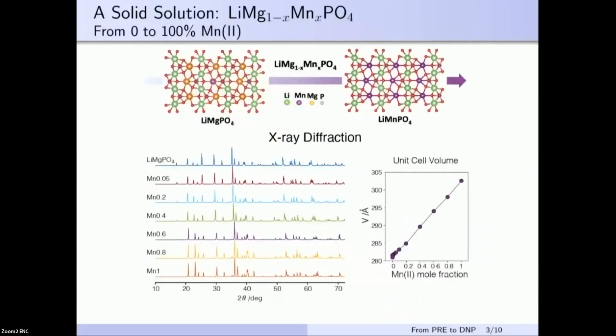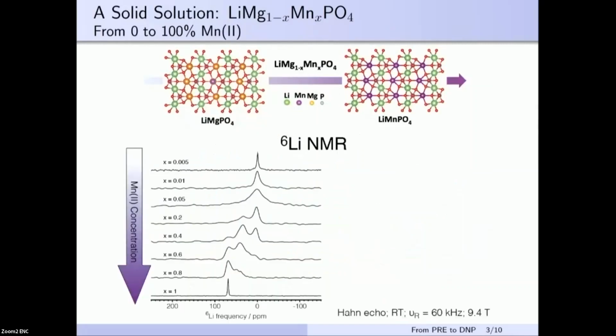And so for that, we prepared a series of samples of composition lithium magnesium manganese phosphate. We chose this system because here we are able to substitute the diamagnetic magnesium by paramagnetic manganese from 0 to 100% without altering the crystallographic structure, as we verified with X-ray diffraction. Another reason we chose this system is that it has a couple of NMR-friendly nuclei.